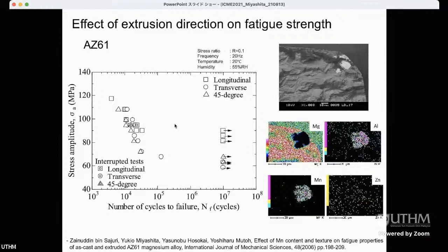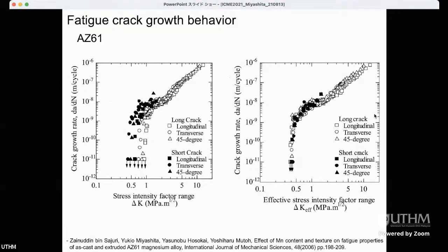As you can see from this figure, we can recognize the effect of extrusion direction on fatigue strength characteristics. According to the fracture surface observation, in most specimens in this test we could observe an inclusion as a fracture origin. In this case, aluminum and manganese were detected by EDS analysis at the fracture origin, the inclusion. We also carried out a fatigue crack growth test with the same material. As you can see from this figure, fatigue resistance also depends on the extrusion direction, affected by the relation between loading direction and extrusion direction.